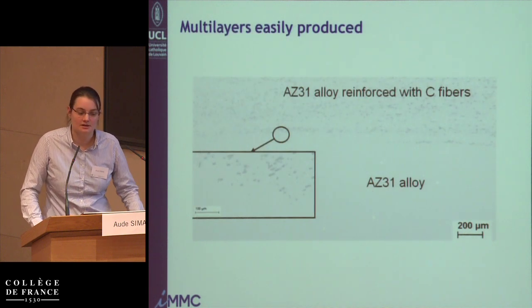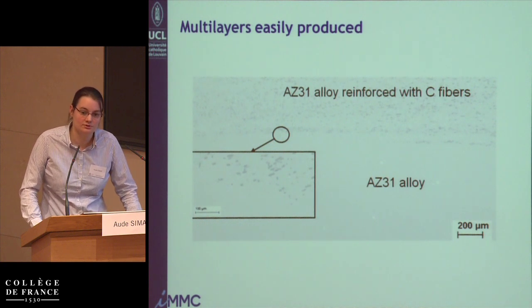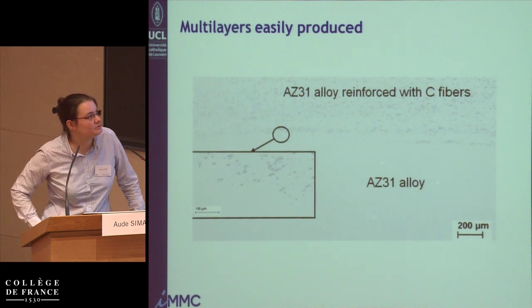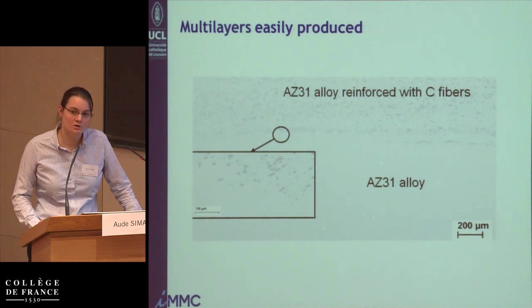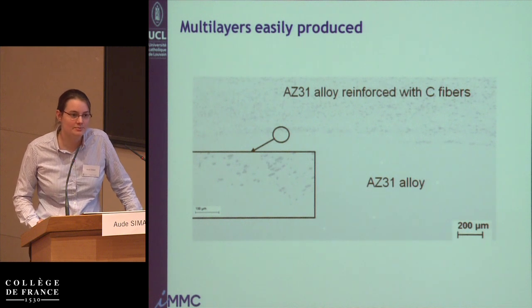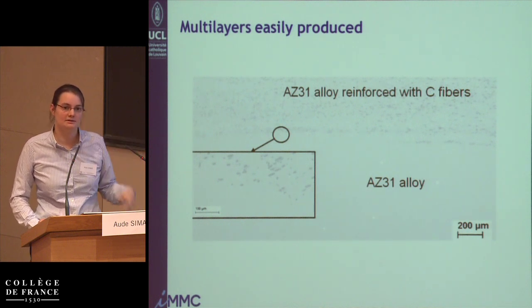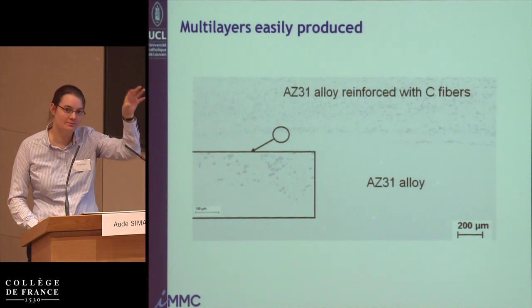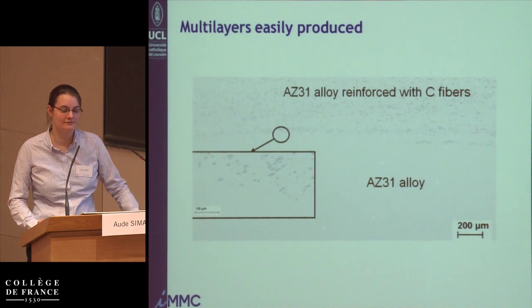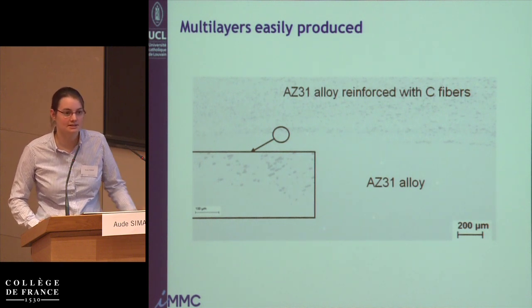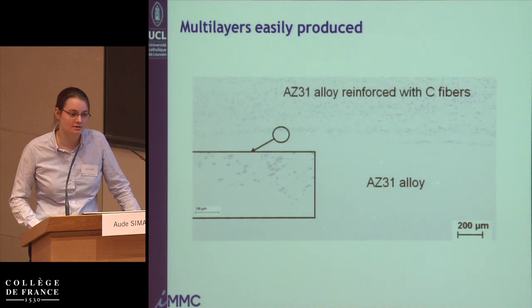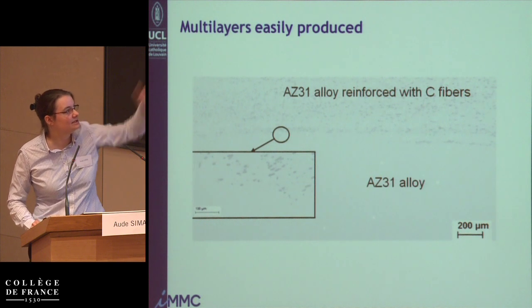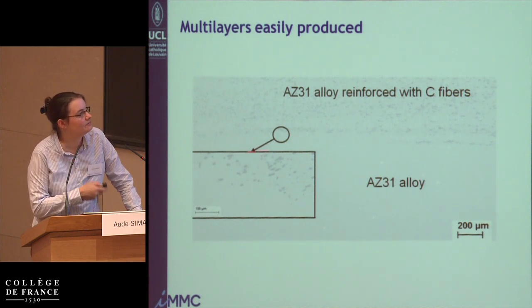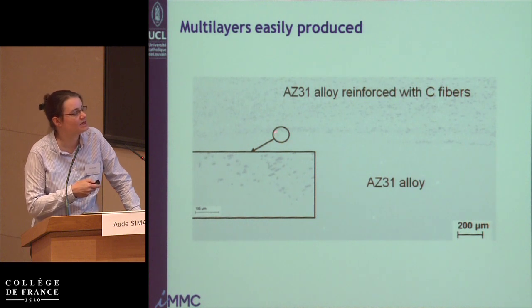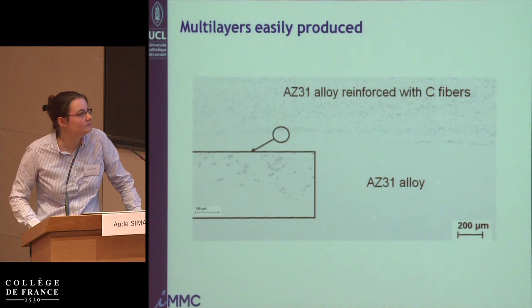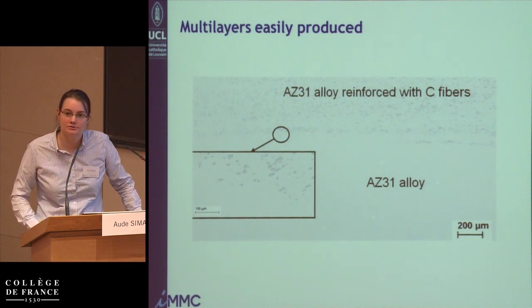So you see that with this kind of process, you can produce also heterogeneous architectural materials. You can produce materials that have a reinforcement where you want the reinforcement to be. I didn't mention that for the copper material, but you can make a graded material with the yttrium oxide particles on top, and then that would have a better wear resistance at the surface, and then a core that is more ductile. And you can do that here, and this is a typical picture to show you that we can have a quite sharp interface between the region where you actually have carbon fibers and the region where you only have the base material.